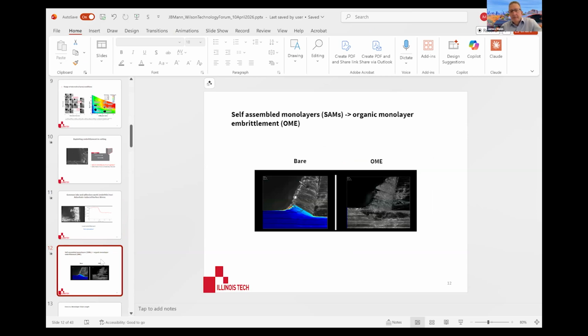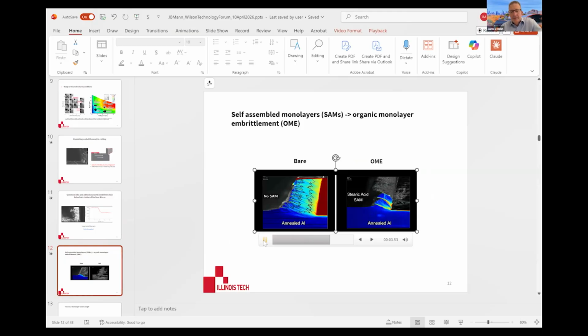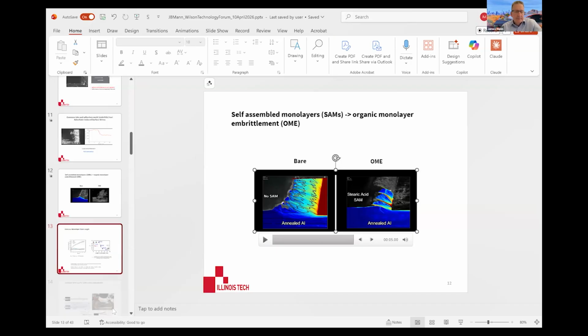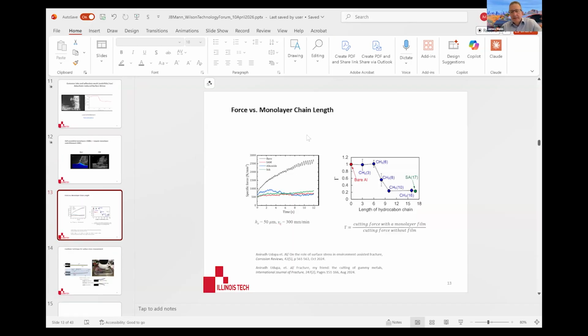It can even be done using self-assembled monolayers. So a monolayer of media, an organic media, and this is another example using this videography or high-speed imagery. You can see on the left is no self-assembled monolayer. On the right-hand side happens to be with stearic acid as a monolayer. So you can see the drastic effect it has on not only the shear, but the morphology of the chip itself. And we're studying what happens at different chain lengths of these monolayers. And it turns out that there's a critical chain length of, in this case, 6 for a hydrocarbon chain where the effect becomes relevant. So we've been studying different media, inks, alkoxide effects, alcohol.